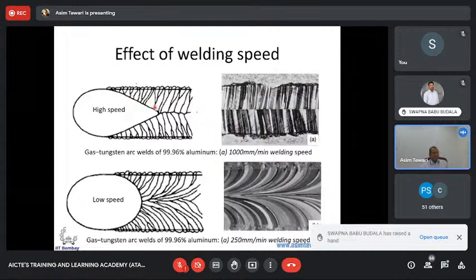Now this is a single weld bead. Depending upon the speed, if it is very high speed versus low speed, the structure of the grains being formed could vary. So what you now need to understand is that not only are distortion and residual stresses important, which can be mitigated by your process variables, but your process variables will also have an immense effect on the underlying microstructure. Thus, you need to optimize your process variables, not just to keep residual stresses low, but also for a specific microstructure.